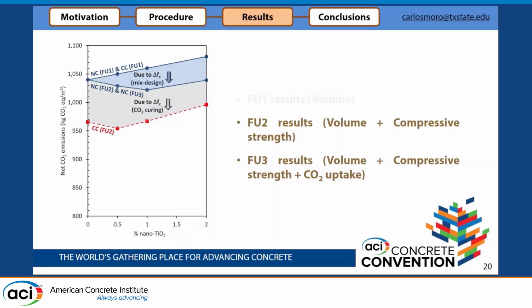We also calculate the functional unit 2, that means volume plus compressive strength, of the CO2 cure samples. And this is further improved because of the increase in compressive strength that happens during the carbonation process, during the CO2 curing process. And in that case, a small amount of nanoparticles still decreases the global warming potential compared to the reference sample, but if you add 2%, right now it is not good for decreasing the global warming potential, right? Like the net CO2 emissions.